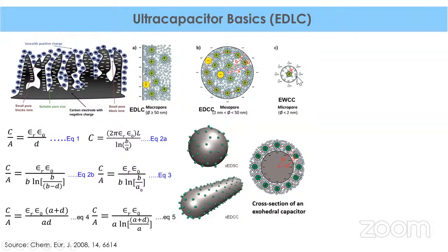In the case of micropores, these are so small, less than 2 nanometers, and even solvated counter ions have a size of around 1.7 nanometers if we consider aqueous acidic electrolytes like H2SO4. So sometimes solvated and sometimes desolvated counter ions enter the pores, and they line up to form an electric wire in cylinder, because probably only one counter ion can enter such a small pore. So they form a kind of wire in cylinder capacitor, called EWCC.